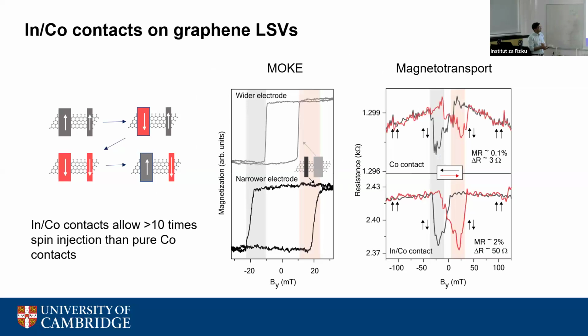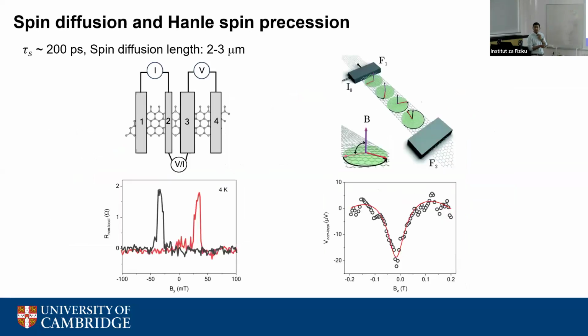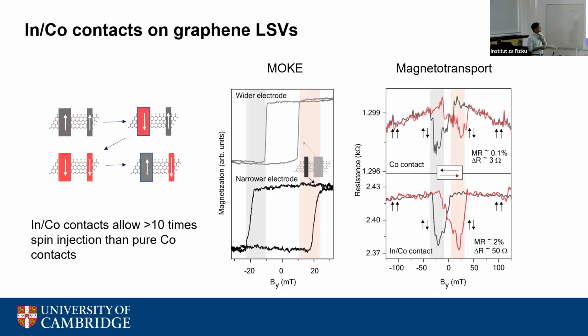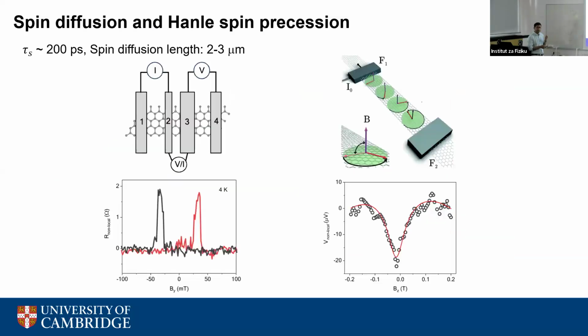This is just magnetotransport, but if you want to show pure spin transport, you have to do something called a non-local measurement, whereas all of this is a two-terminal measurement, where you apply voltage and current from the same terminal. If you want to measure pure spin currents, you source current from the first two terminals, and the spins diffuse to the second and third, and you measure the voltage across the other terminals. So this is called spin diffusion.